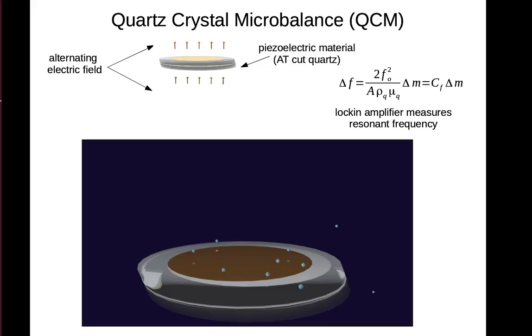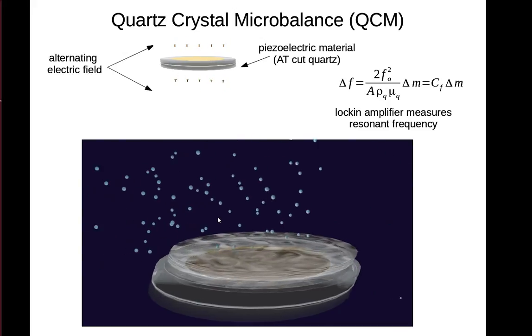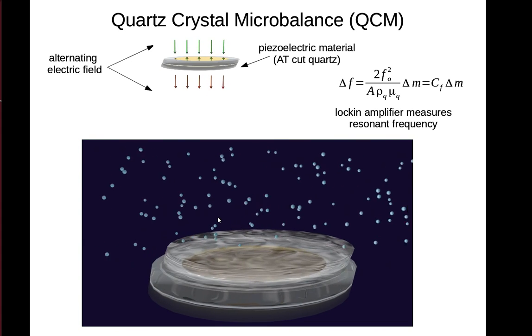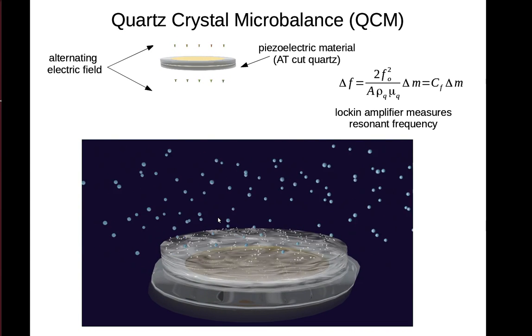By putting a material on top of the crystal, it changes the resonant frequency of the oscillation. The resonant frequency of the oscillation is related to the mass through some constants, physical parameters of the crystal itself. We use a lock-in amplifier to measure the resonant frequency, therefore knowing the change in mass over the time of the experiment. The experiment begins by spin coating a polymer on top of the crystal and then flowing a buffer solution of interest over top.